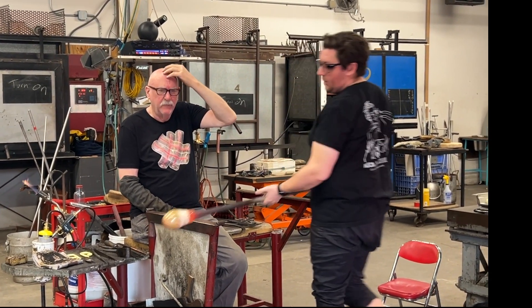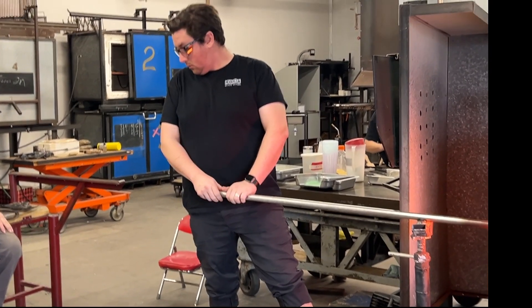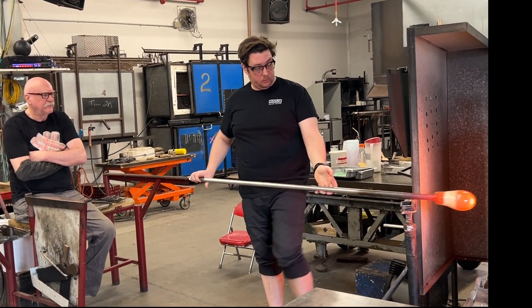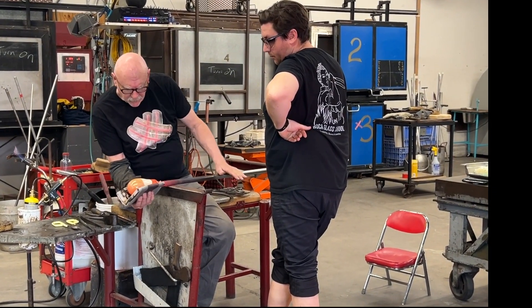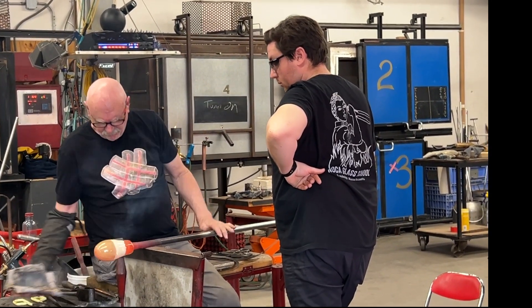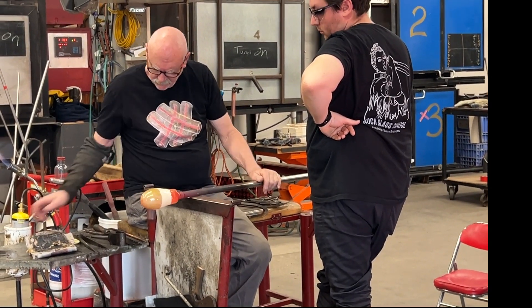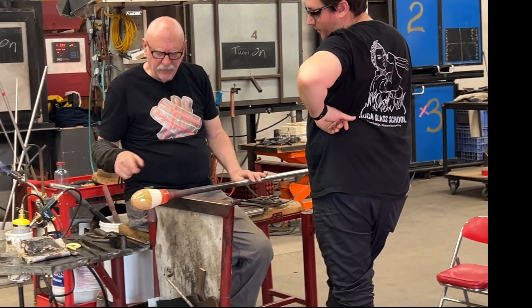They're letting this cool out a little bit. That dark stuff you see on there — that's just a little of the block burning. When they go in the glory hole, it burns right off. You have to let it cool down a little bit before you gather the hot glass; otherwise, if your starter bubble is too hot, by the time you get back it will just be all foggy. Back in Roman and medieval times, they would use bunches of wet cane to fold in their hands and shape the glass.